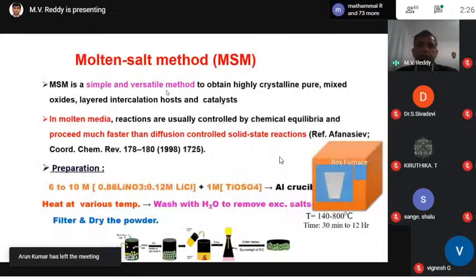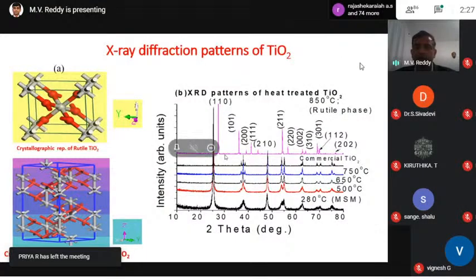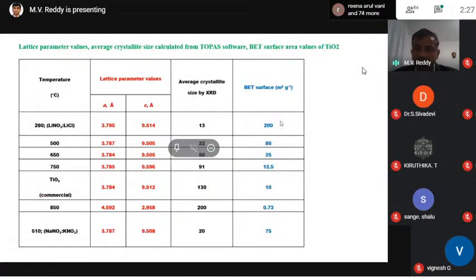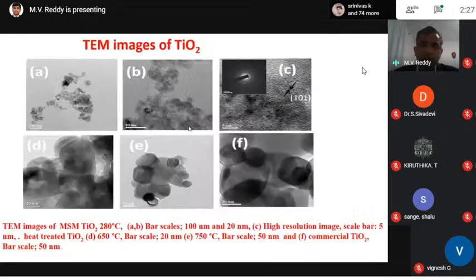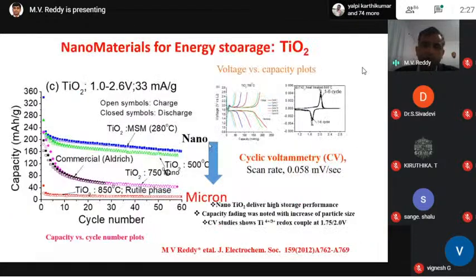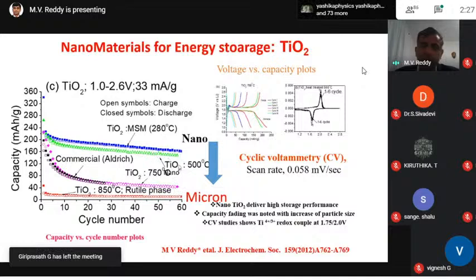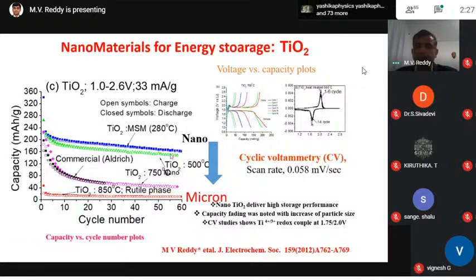Again, for TiO2, people can prepare it by the molten salt approach. These are the typical XRD patterns from low temperature to high temperature; the surface area decreases when we heat the sample at different temperatures. We have to see how the lattice parameter changes. Since these are intercalation type compounds, we need a little more surface area and an appropriate crystalline particle size. It clearly shows that if you go from nano size to some micron size, the energy storage performance decreases, especially for this type of titanium based oxide, anatase phase, etc.